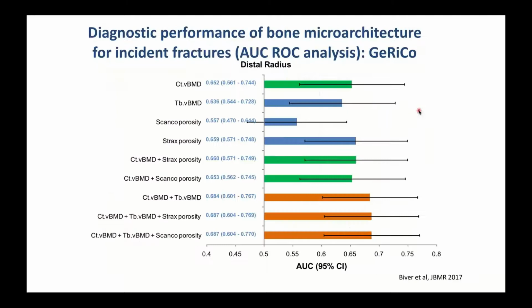To the point that when you want to predict incident fractures by porosity, the SCANCO porosity does not. That's the AUC, area under the curve, for incident fractures, but the StrAx porosity does and adds to the prediction of other microstructural parameters. So my second point was to say, if you want to analyze porosity as a determinant of bone fragility in general and in diabetes in particular, you need to be careful which tools you use to quantify that cortical porosity.